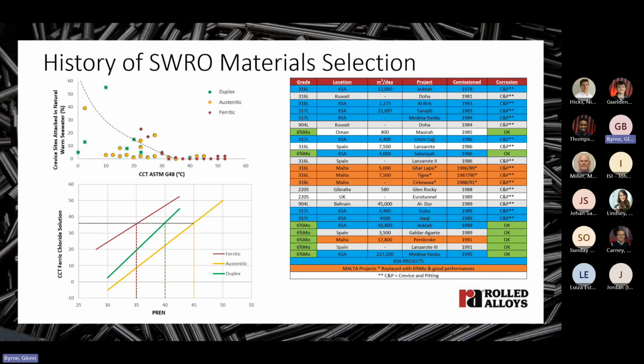You can see from the table that unlike Shell, this industry's alloy selection strategy was to do this by rote, starting with 316L and escalating alloy content and cost until a satisfactory level of corrosion resistance was realized. And you can see this in the Saudi progression of projects. I've highlighted these in blue. So the early Saudi projects, 316 and 316 here, and then they didn't work out so well because they suffered pitting and crevice corrosion. So they were moved to the next alloy up, 317. That suffered crevice and pitting corrosion, and then they gravitated to 6% molybdenum alloys by around about 1986. So from 81 through to 86, it was trial and error, but the 6MO worked quite well.